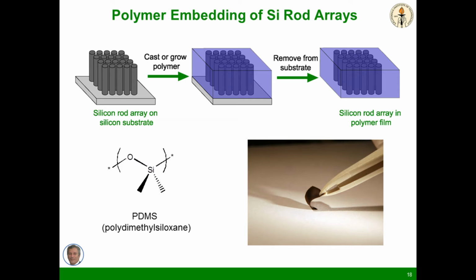But that would just be a stunt. It wouldn't look like the pieces that we needed in our architecture, except that then we put a piece of plastic in there. We do that with essentially a tube of fish tank goop that you could buy at the pet store. That's exactly where this one was bought. It's fish tank sealant called RTV, or chemically polydimethylsiloxane, which when you fill it up has this interesting property that if you peel it, the rate of its peeling affects its flexibility, much like a Band-Aid on hair. If you peel it very slowly, the polymer just comes off. You peel it very quickly, the polymer is stiff and the fibers come off with it. And so we give this a yank and rip off those fibers, and we make this material that has the micro rods embedded and still oriented in a piece of plastic that we can peel off and use as one of these pieces in our films.